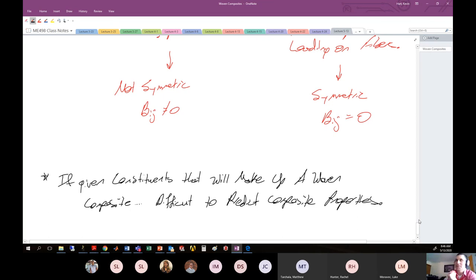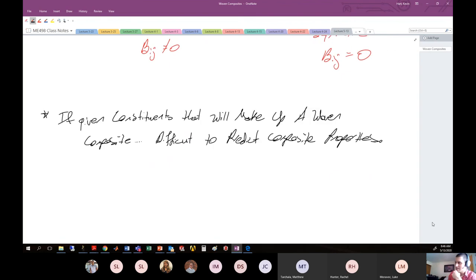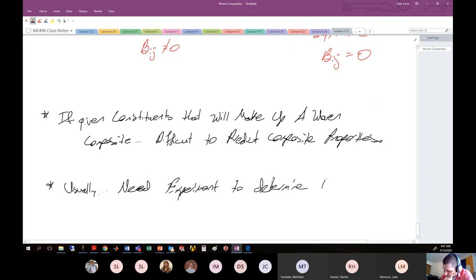So trying to predict what the composite properties will be based on just the materials alone is really hard to do because you don't have information about, let's say, the level of crimp of the fibers or the radius of curvature of the fibers in the weaving process or how much fiber breakage there was during weaving and so on and so forth. Okay, so it's really difficult to predict it beforehand with just the properties of the constituents alone. Okay, so usually you need an experiment. And that's usually what's done.